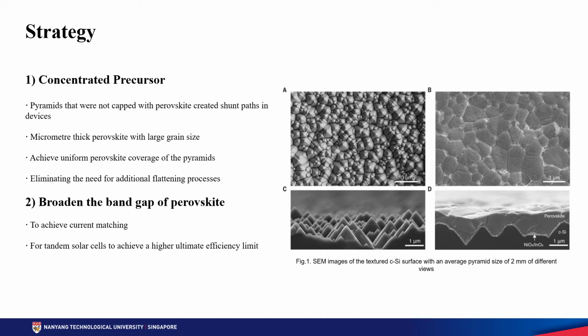Okay, so I come to my part of the strategy. The author first introduced the strategy of concentrated precursor. When the perovskite film was deposited under conventional planar perovskite fabrication conditions, the pyramids that were not capped with perovskite were exposed, and these regions created shunt paths in devices. So the authors naturally used the concentrated precursor to completely cover the pyramids. This results in a micrometer-thick perovskite over the pyramids with large grain size.